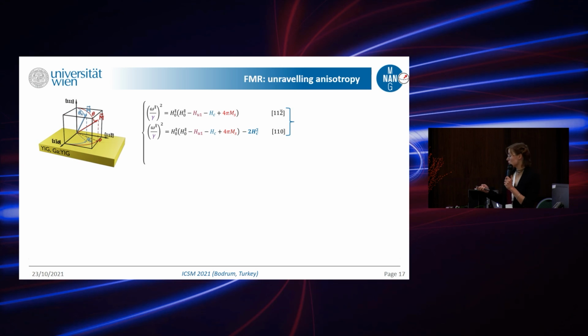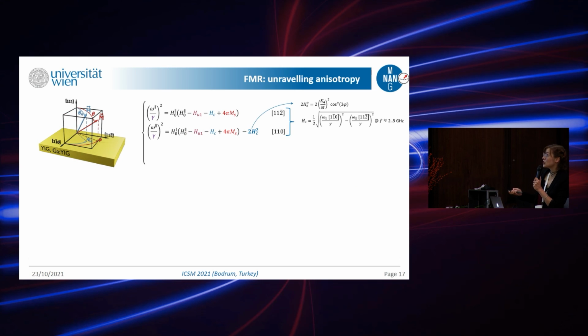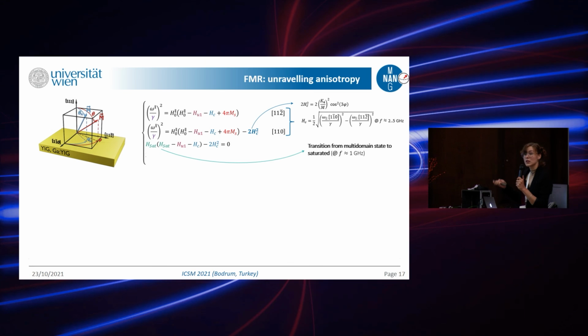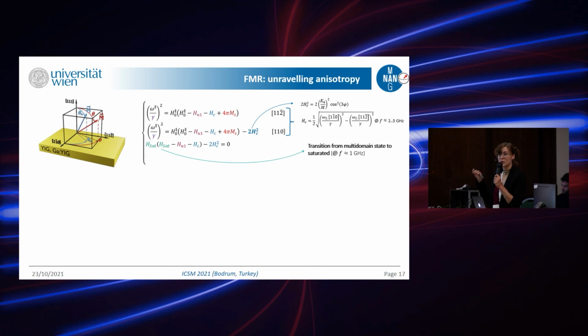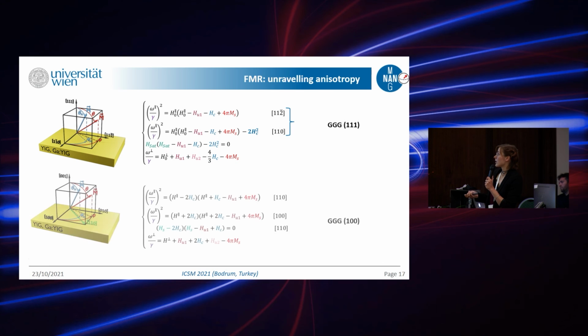We arrive at this set of equations. So for the GGG 111, we are now looking at the cubic anisotropy, uniaxial of the first order for the in-plane, and of the second order for the out-of-plane. Having this set of equations, we are able to fully characterize our material. And in the case of material on GGG 100, the same. Also pay attention that the bottom equations are different from the top one. If you do not carefully perform the characterization, you will get very different results, and you will not get the proper Gilbert damping, proper fields, or saturation magnetization.